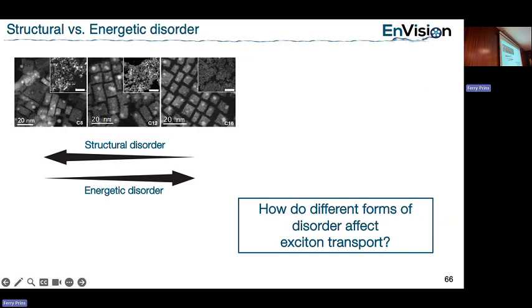So it's very difficult to make really tiny particles monodisperse. Then we're getting into what they now refer to—and David Norris as well, probably a series of articles on these—calling them magic-sized nanocrystals. To be able to synthesize that and take it to industrial scale is a whole separate story. The magic-sized nanocrystals are the same thing as what people have been doing with gold nanoparticles in catalysis, where people talk about clusters more than nanoparticles. It seems that now they're getting a handle on doing that with cadmium selenide, to really have every particle being the same number of atoms. But it's very difficult to make a very good blue emitter for that reason, because you need to go to very small particle sizes.